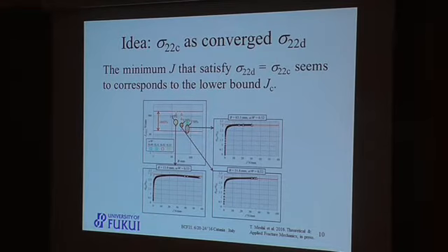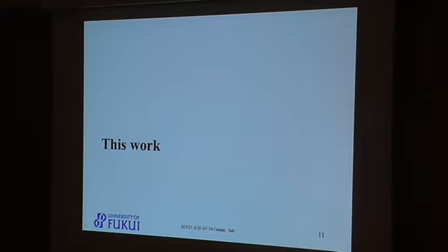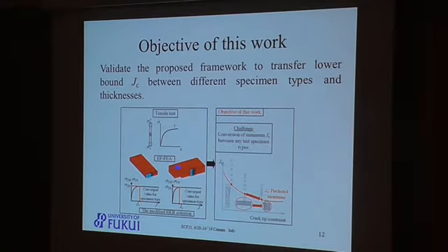Considering the fact that fracture always initiated after sigma 22D reached sigma 22C, we thought that the minimum J that could satisfy sigma 22D equal to sigma 22C must correspond to the lower bound fracture toughness for the specimen and the material considered. Given these observations, we thought that the lower bound fracture toughness for different specimen types and thicknesses can be predicted by predicting the minimum J that could satisfy sigma 22D equal to sigma 22C by calculating EPFEA with a given stress-strain relationship. Thus, the objective of this work was set to validate the proposed framework to transfer lower bound JC between different specimen types and thicknesses.